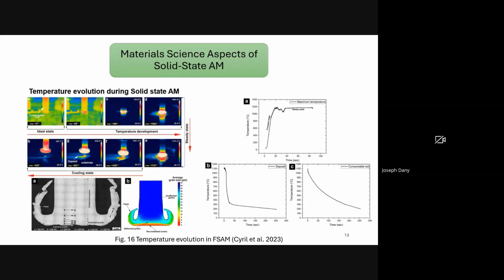The advantages of low and localized heat input are: it minimizes the distortion and residual stresses, since only a narrow zone is heated without affecting the bulk of the substrate. It prevents large heat affected zones and thereby maintains the integrity of the base material. It reduces the oxidation and thermal degradation as the material is not held at elevated temperature for long periods. It limits the grain coarsening in the deposited layer, preserving the refined microstructure achieved by dynamic recrystallization. And also, it allows better property retention, making the deposited surface layer suitable for high performance applications.